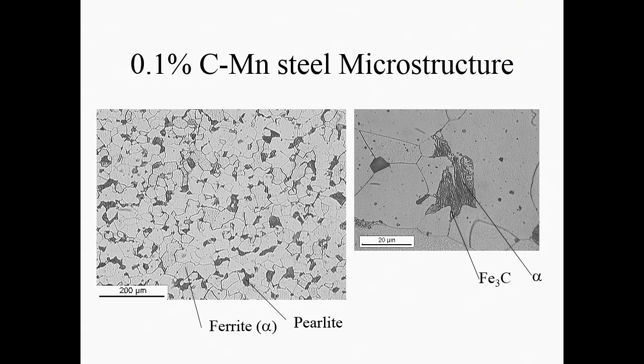So if we look at a typical 0.1% carbon manganese steel, this is a structural steel with girders, bridge plates, pipeline materials. They all look similar to this. What we have, again in a polished and etched cross section, we have these white grains here and then these darker regions here. And when the first metallurgists looked at this, these dark areas shimmer a bit like mother of pearl, so they called it pearlite, ITE. And when they looked at this, this is pure iron as far as they were concerned, so fer for ferrous, and then ite, because it's a solid phase. So most solid phases in descriptions, the metallurgists call something ite. And that's what you can see on the surface there.